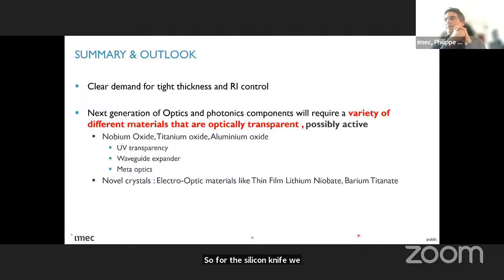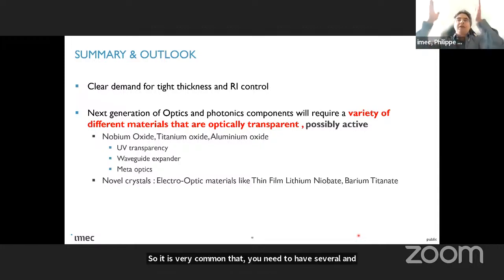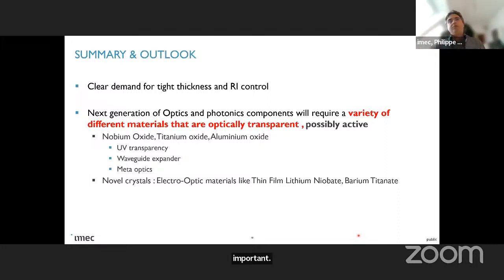In the world of optics, clearly we are relying on the refractive index contrast. So you need to be able to deposit these thicknesses very uniformly. You need to be able to pattern them. We are talking about pillars technology. So it is very common that you need to have several hundred nanometers of thickness of a layer and sub-100 nanometer pillars. Depositing the layer and being able to etch it is very important. And then you have the next step, which is to put oxide, the lowest index material. You need to be able to do gap fill.